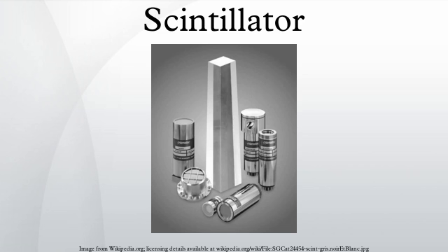NaI(Tl), or sodium iodide doped with thallium, is by far the most widely used scintillator material. It is available in single crystal form or the more rugged polycrystalline form. Other applications include nuclear medicine, basic research, environmental monitoring, and aerial surveys. NaI(Tl) is very hygroscopic and needs to be housed in an airtight enclosure.